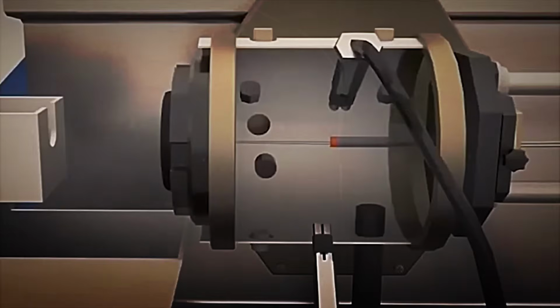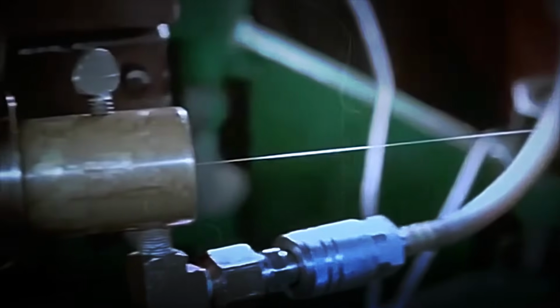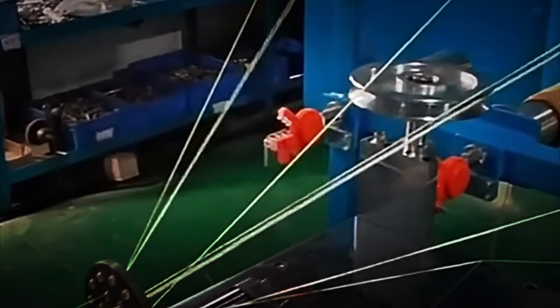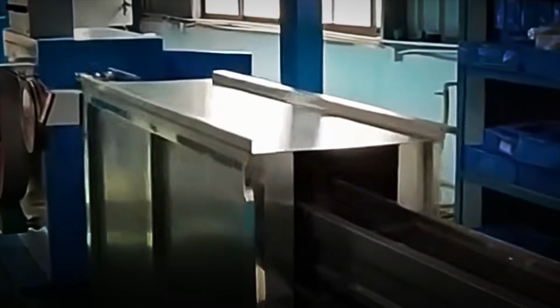Upon exiting the oven, the fiber passes through a coating machine that immerses it in a channel filled with liquid polymer. This first coating forms a soft, flexible inner layer that absorbs impacts and allows the fiber to bend without breaking. The yarn then passes through a second channel that applies a more rigid outer layer designed to resist abrasion, moisture, and dust. The two layers serve complementary functions. The inner layer provides cushioning, and the outer layer provides structural rigidity. These coatings are applied in fractions of a second.